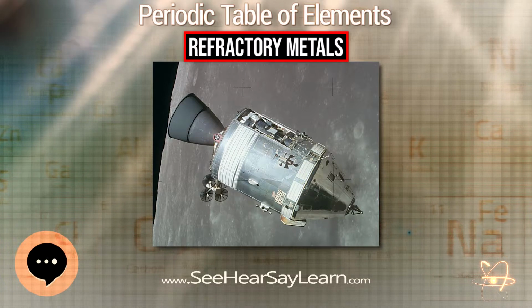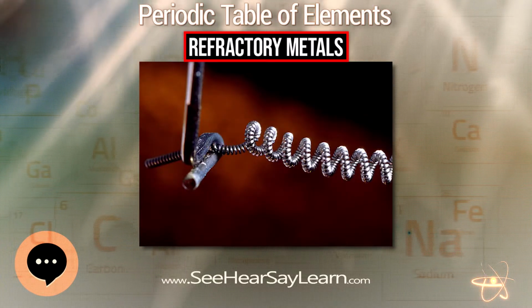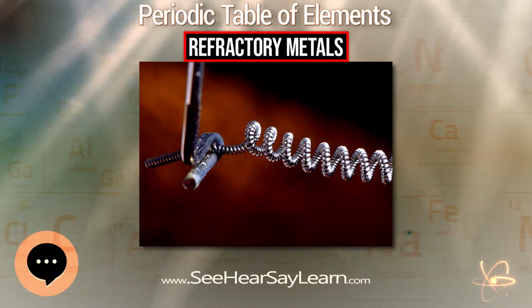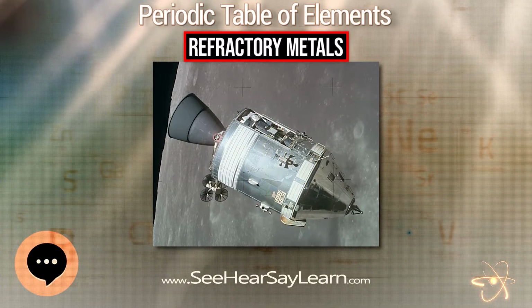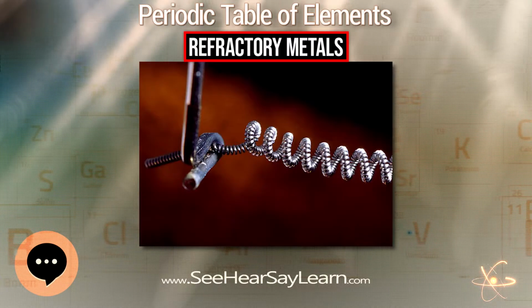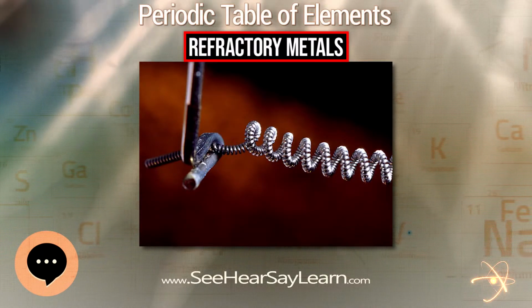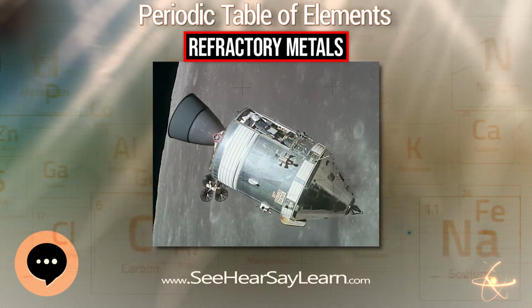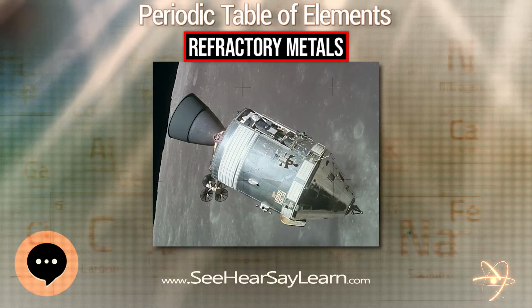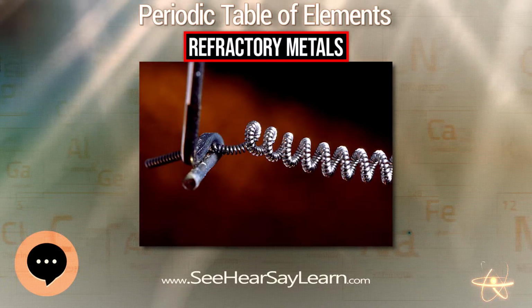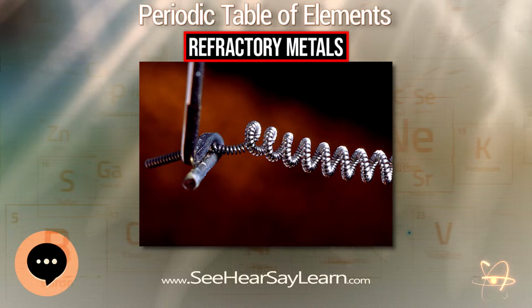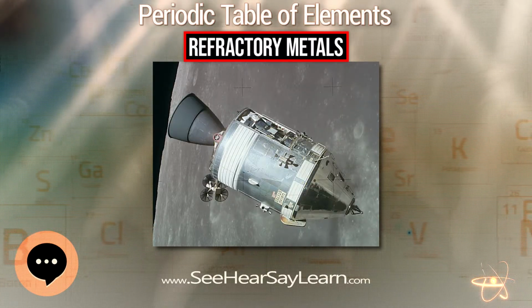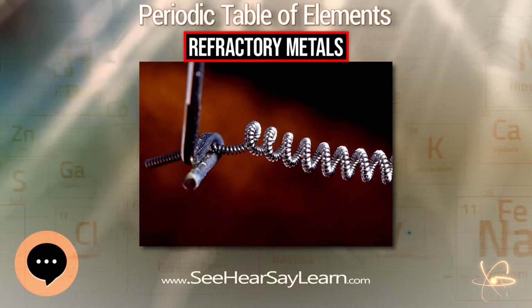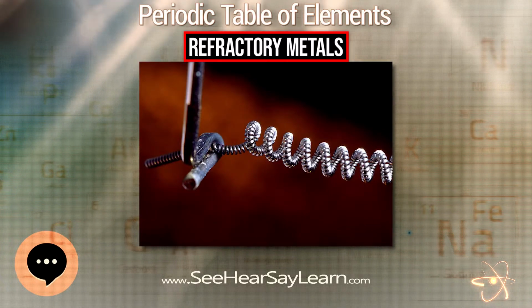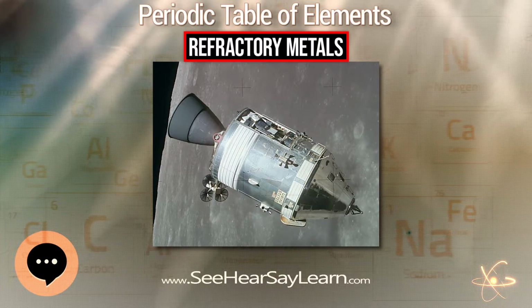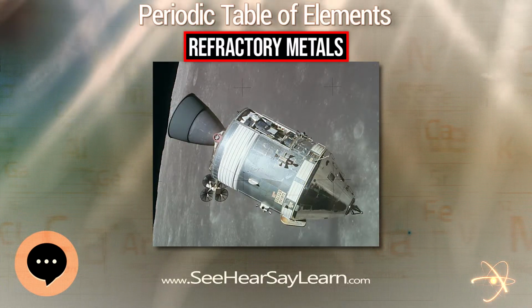Its most important use is as a strengthening alloy of steel. Structural tubing and piping often contains molybdenum, as do many stainless steels. Its strength at high temperatures, resistance to wear and low coefficient of friction are all properties which make it invaluable as an alloying compound. Its excellent anti-friction properties lead to its incorporation in greases and oils where reliability and performance are critical. Automotive constant velocity joints use grease containing molybdenum. The compound sticks readily to metal and forms a very hard, friction-resistant coating. Most of the world's molybdenum ore can be found in China, the USA, Chile, and Canada.